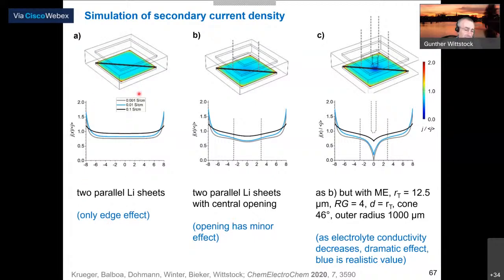If we have 2 parallel lithium sheets, we have a homogeneous current density distribution for different concentrations of electrolyte, just an edge effect. If we have an opening here, which we need to insert the microelectrode, we see a small variation, but it's still a tolerable change in the current density distribution. But if we have our microelectrode at the working distance, then we see a strong drop of the current density if the microelectrode is close to the sample of interest when we do the charging discharging routines.